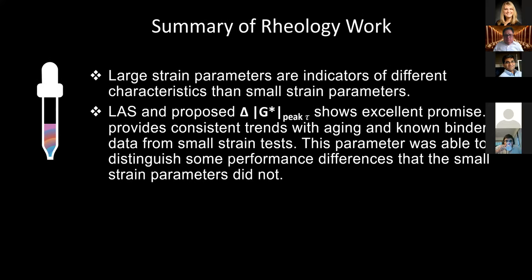Continuing, the large strain parameters are indicators of different characteristics than the small strain. The linear amplitude sweep and the proposed delta G shows excellent promise. It provides a consistent trend with aging and known binder data from small strain tests. This parameter was able to distinguish some performance differences that the small strain parameters did not.